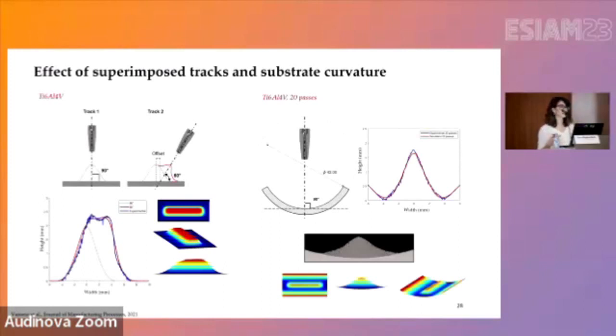So the analytical model that has been developed has a very high potential to capture the shape and evolution of the shape of the track, as we are changing different process parameters, including angle of impact, number of passes, standoff distance, and velocity of the nozzle.